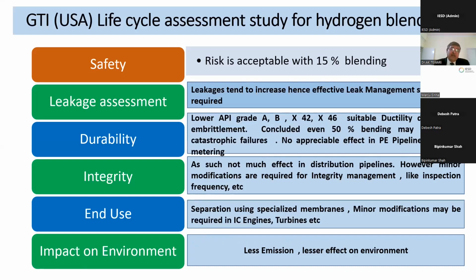And they also indicated one very vital point, that lower grade API pipe, the steel pipe you use in the industry for transportation, up to X42, X46, and even X52 is suitable. Sometimes we have X70, we have gone for that, but higher grades like X80, X100, even X70 to the extent possible, should be avoided. They concluded up to 50% in this lower grade. Lower grade means low tensile strength steel.